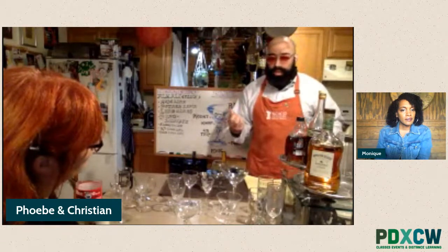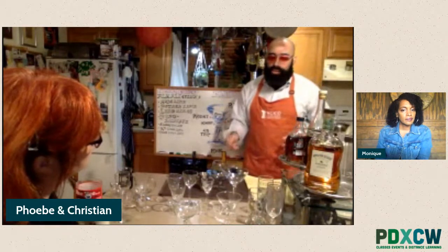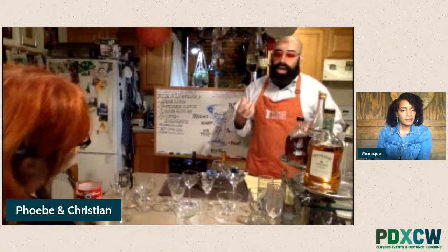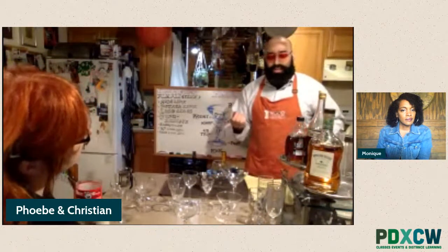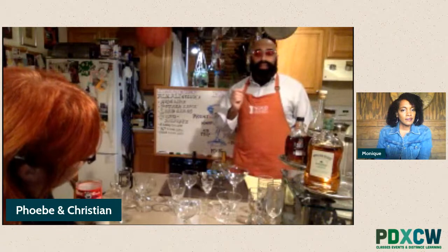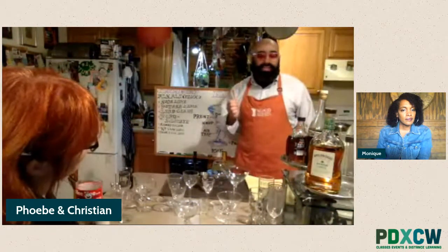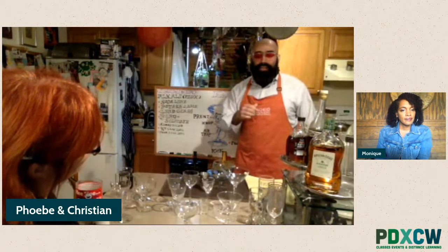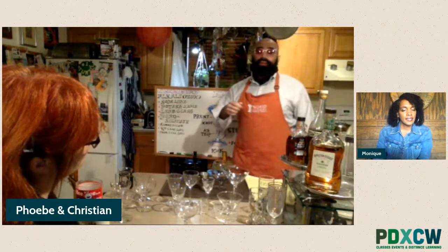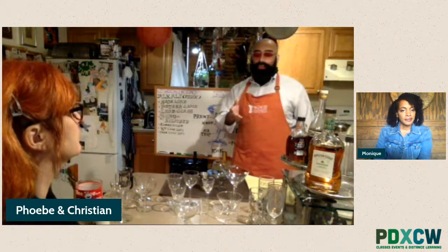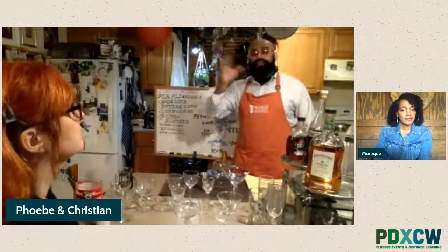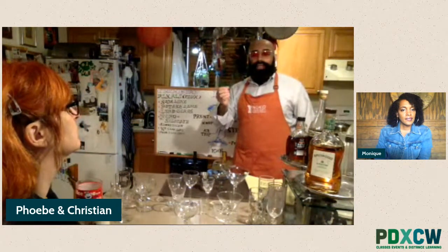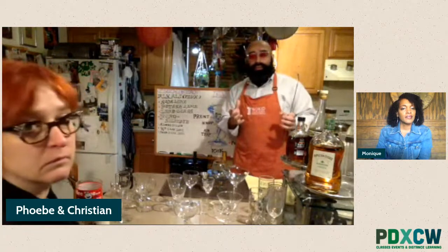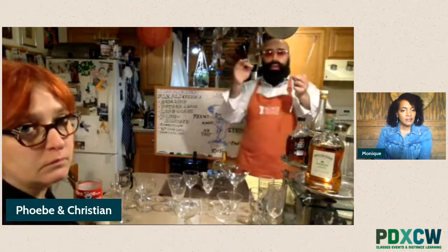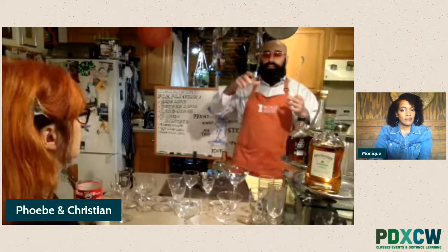Now, how lead glass varies from soda lime glass and potash lime glass is that it's softer but denser than the other glass. And what that allows it to do is it gives it a little bit more strength for its size. Now, does that mean that crystal is more robust than soda lime glass? Well, that depends on what you do with it. When it comes to crystal, one of the purposes, to take advantage of its greater strength, is they make it thinner. They blow it thinner, so that you end up with a finer rim.